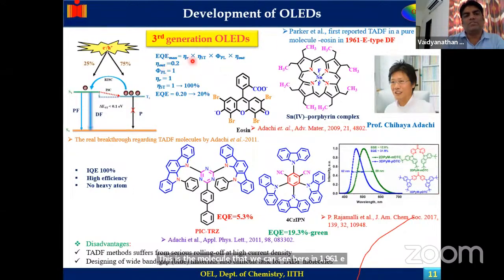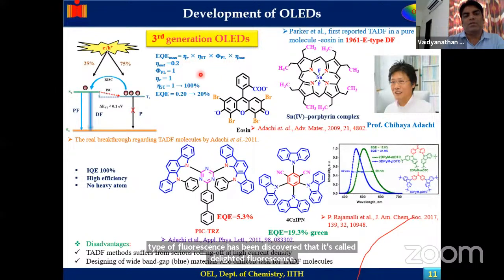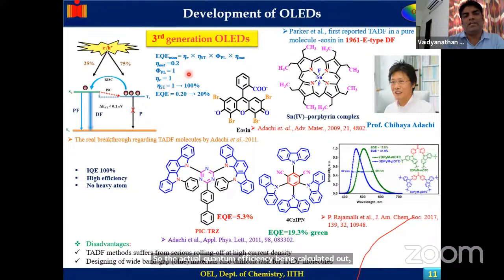So the external quantum efficiency has been calculated. The outcoupling is 0.2, the PL quantum yield is 1, and eta radiative transition is 1. The singlet-triplet transition can be 100% possible. So hence one can get an external quantum efficiency of 20%.